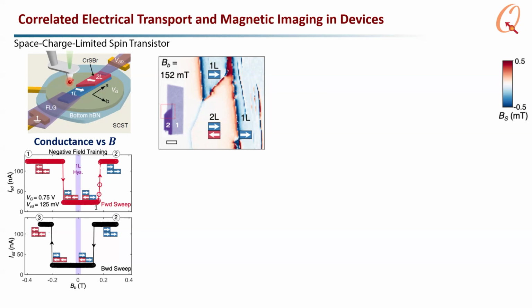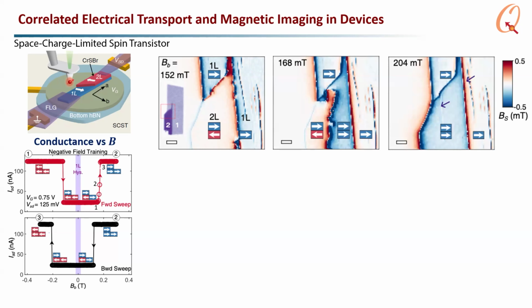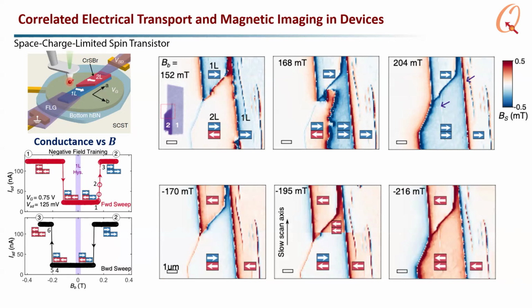We can just go ahead and map that as we take electrical measurements, and then we see that when you have a gradual transition, there is a domain wall sliding across the bilayer. And when you have a sharp transition, for example, 4, 5, 6 on the way back, that is a coherent rotation of the magnetization of the top layer. So when the domain wall moves across the bilayer, it's in the bottom layer, which is shared by both regions. And when the magnetization switches at the top suddenly, it's just a flip of the top layer.